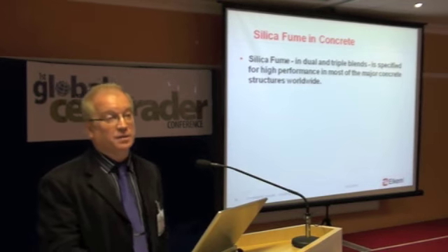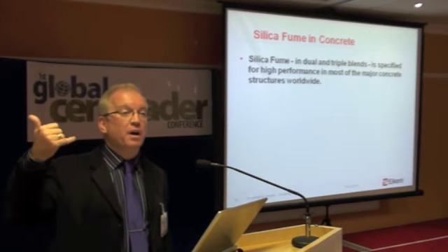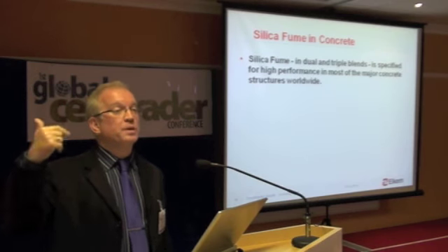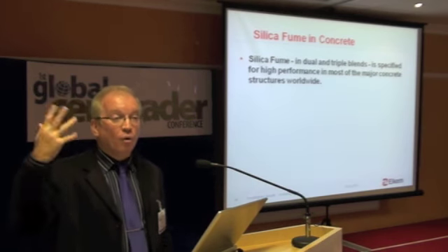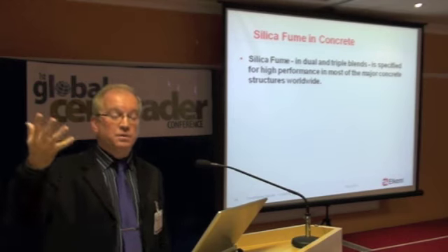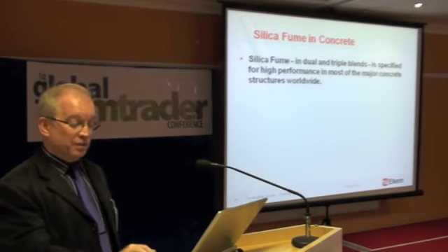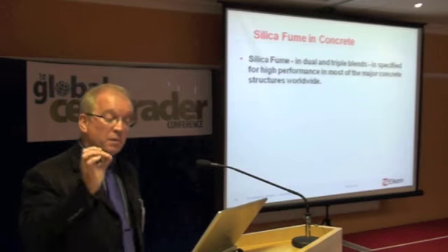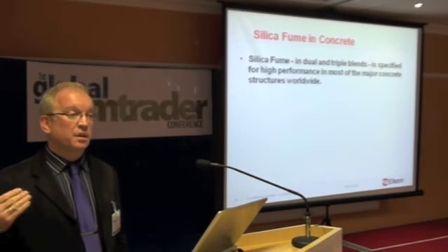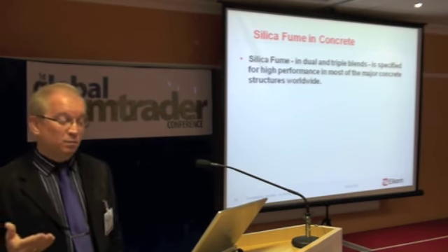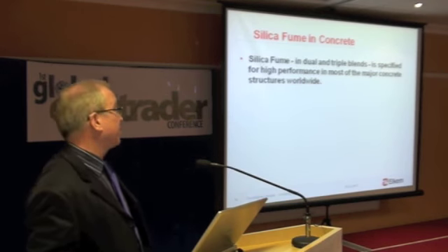Dual and triple blends, we've already heard about. OPC, fly ash and silica fume. OPC, slag, silica fume. All the other materials, the mineral fillers can be used, and rice husk ash, if it's a good enough quality, we can make sure that we can use those blends. Depends on where you are, what's available, to design that mix to get the achievement.